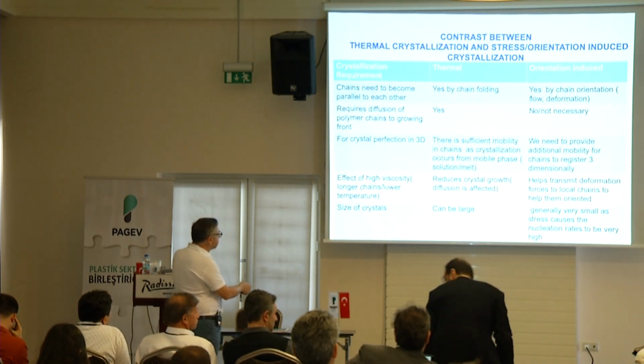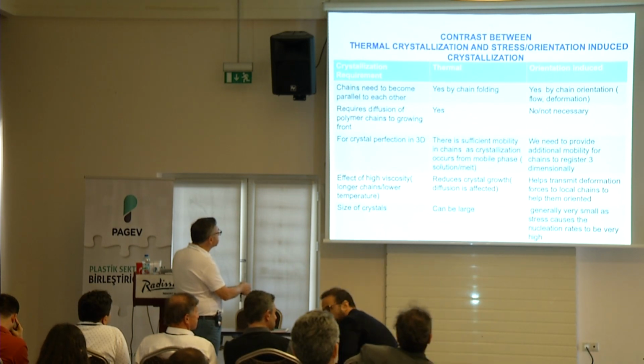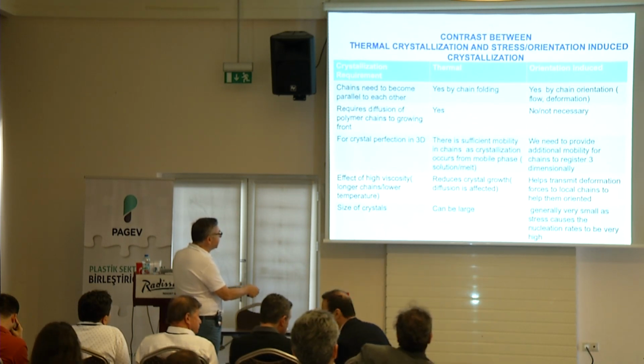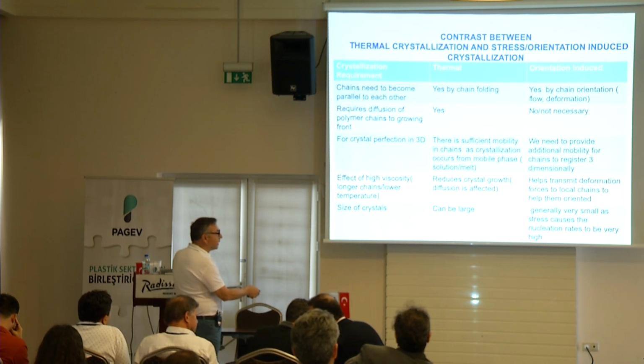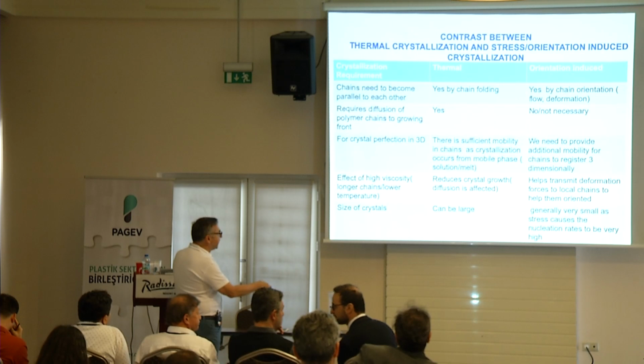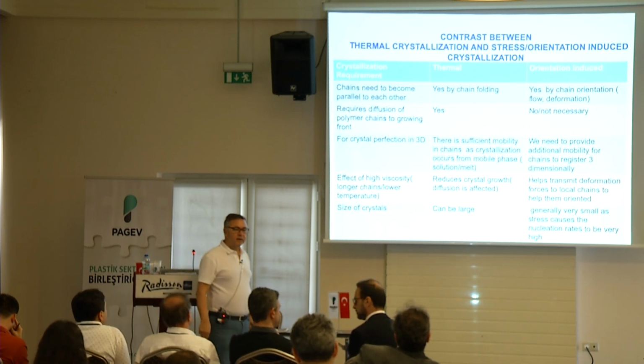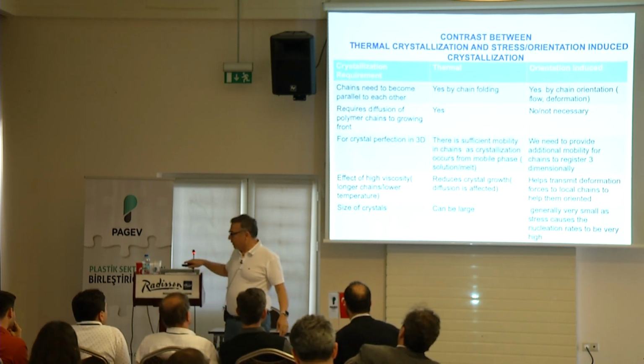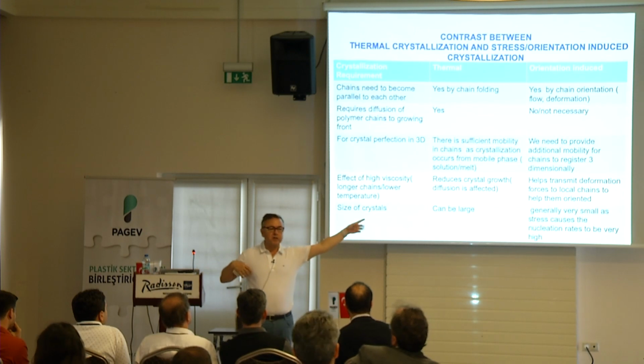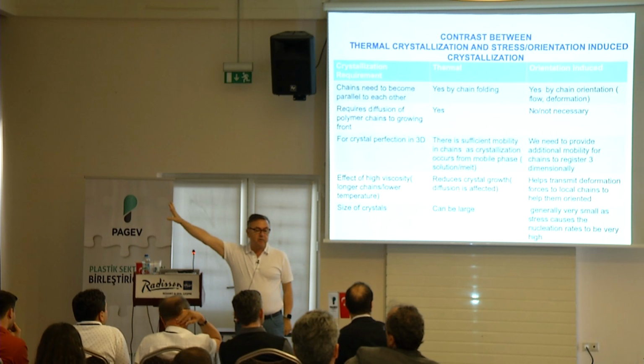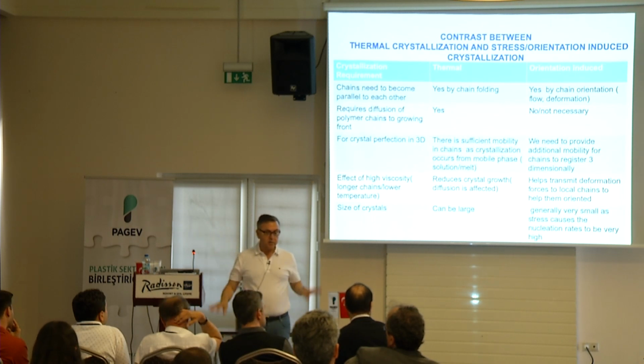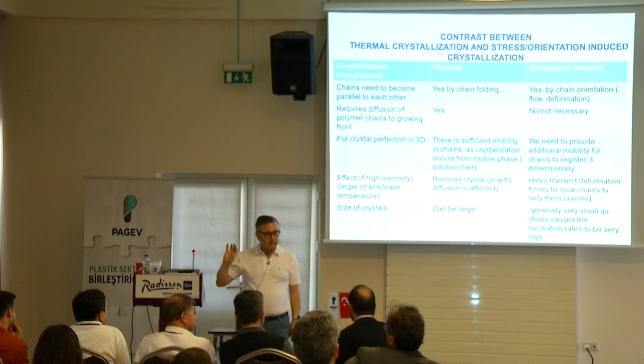So the effect of high viscosity, longer chains, and lower temperatures reduces the crystal growth. Diffusion is affected, right? We know that. But if I increase the viscosity, it helps the orientation. So high molecular weight materials are more dramatically influenced by orientation, and low molecular weight materials are more dramatically influenced by thermal effects. So opposite behavior.